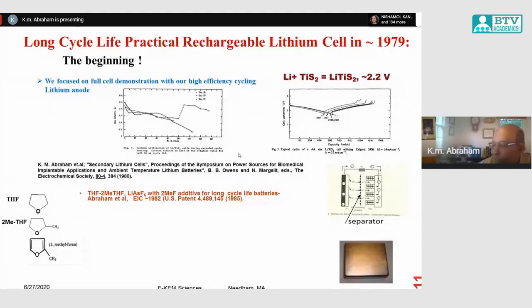That was not good enough for making a practical battery. So what we did was we invented some new electrolytes, ether-based electrolytes. So this is a mixed electrolyte based on tetrahydrofuran and 2-methyl tetrahydrofuran with some small amounts of 2-methylfuran. And we were able to show that using that electrolyte and lithium hexafluoroarsenate at that time as the electrolyte salt, we were able to get, for the first time, batteries with more than 100 cycles. That was an exciting time at that time.